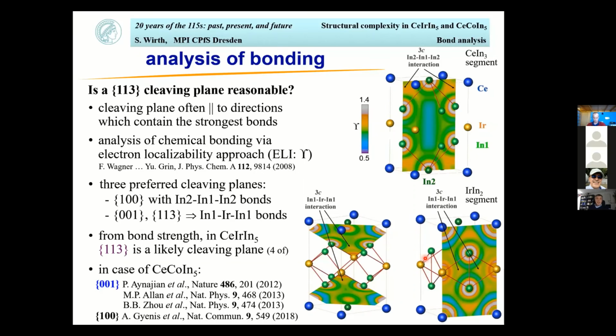Now, from the bonding strength analysis, it makes sense that for the iridium, we have the 113 plane. But I should point out here that we actually can have 4 domains, and that's why the surfaces look so rough. In case of the cobalt, you actually have a preferred cleaving plane along 001, and I already pointed out that this has been observed very nicely. And also very recently, this is another work by the group of Ali Yazdani. Also, the 100 plane has been observed. So all these planes, which Yuri had predicted earlier, actually have now been observed.